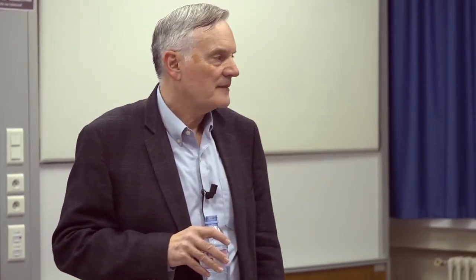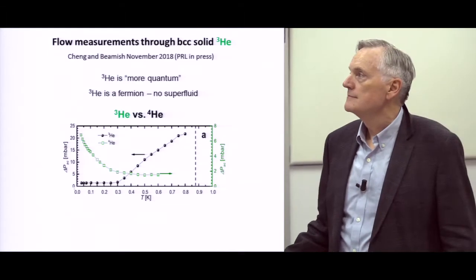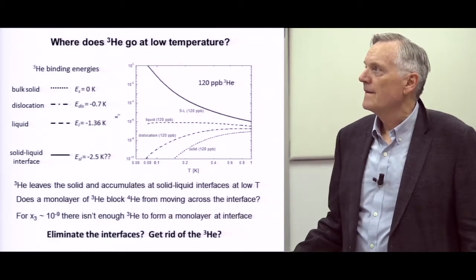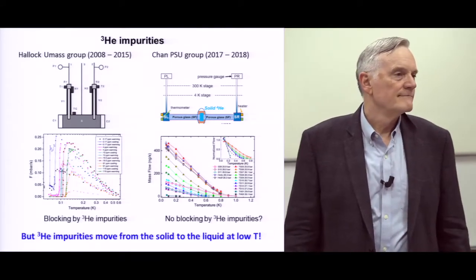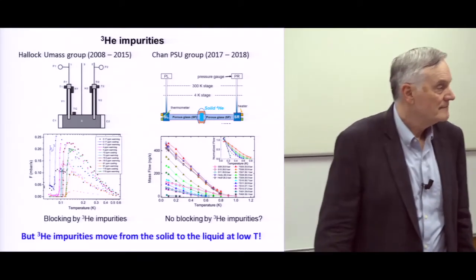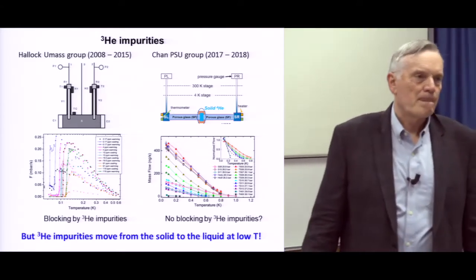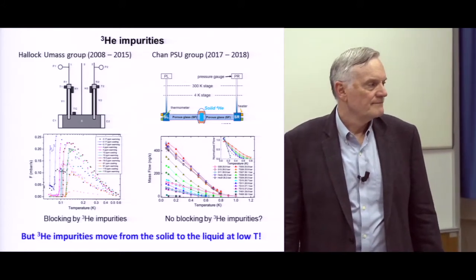Mm-hmm. They see this flow, which you mentioned in the end of the talk, only when they are close to the melting curve. Yes. And this is what I remember as a proof that it's a surface phenomenon. Yeah. It occurs in the roughness of the wall or something like that, where the solid does not enter because it's not wetting. So there remain liquid helium channels at the interface between the copper wall and the solid helium crystal, except if you raise the pressure up, when you force the crystal to invade the roughness of the wall, which exists at atomic size, and then it should disappear. Well, this is exactly what they observe.